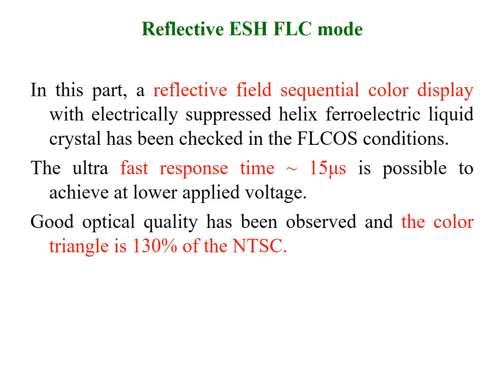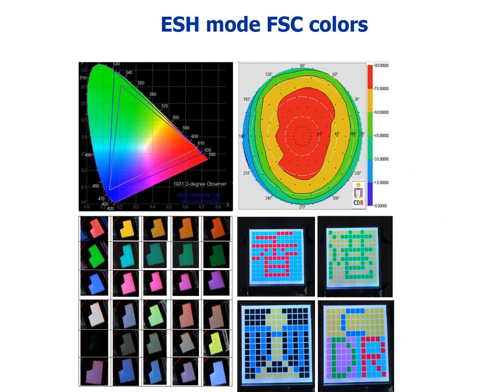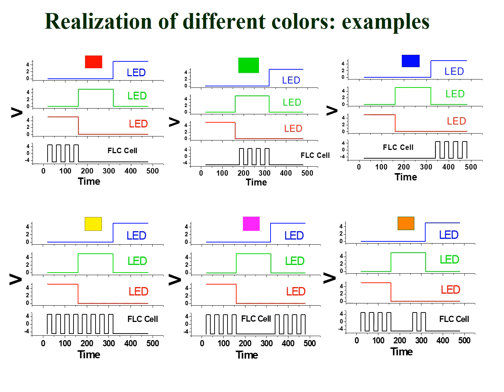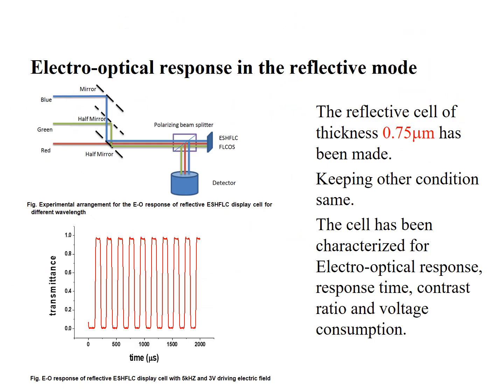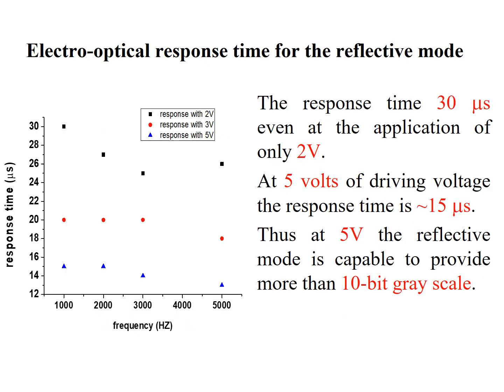So we have 130% of color triangle, fast response time, and the reflective field sequential display without any problems. We also have excellent angles of the display. To make gray levels, we use pulse width modulation, so we can make different gray levels. And because the thickness of liquid crystal is very small, we have no influence. We have no crosstalk between two neighbors.